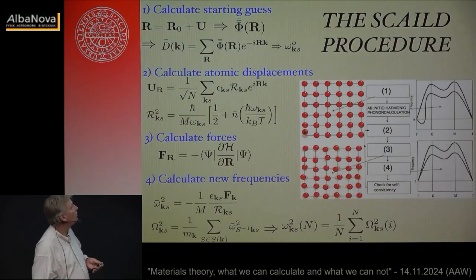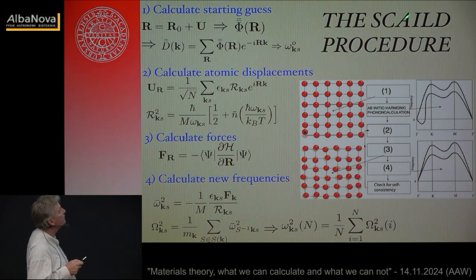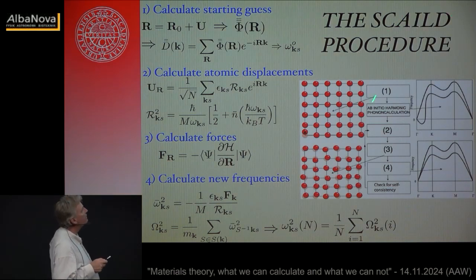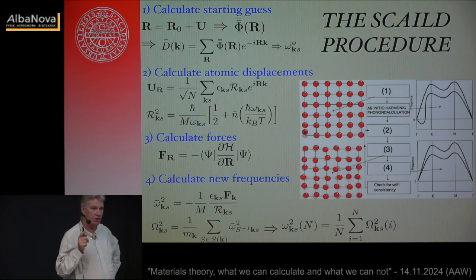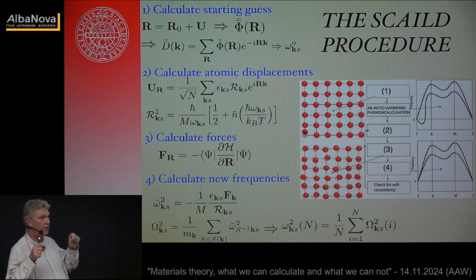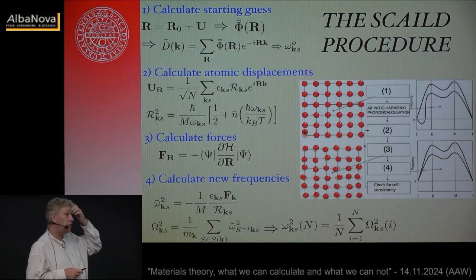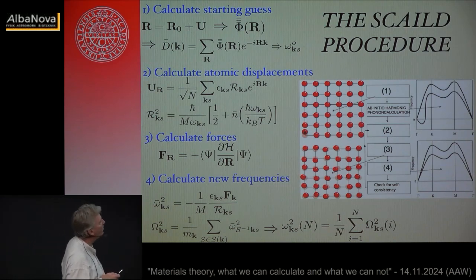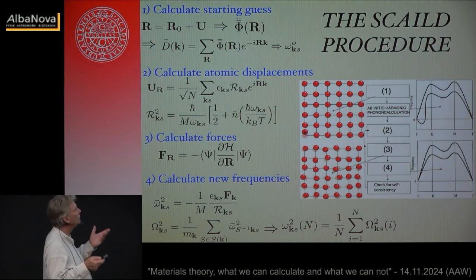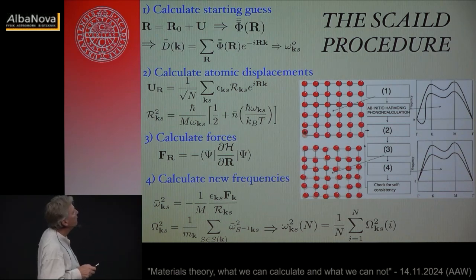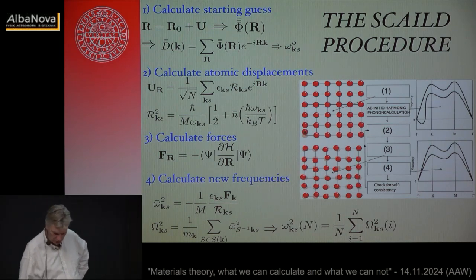So we came up with something we called the SCAILD procedure. SCAILD stands for self-consistent ab initio lattice dynamics. The basic idea is to say, no, it's not correct to just look at this force constant matrix for an ideally situated, perfectly crystalline structure. Titanium is BCC at higher temperatures, and therefore the lattice is not a stationary lattice. Things are vibrating and moving around a little bit, and that vibration, that movement, that entropy, our working hypothesis is, stabilizes this BCC crystal structure, and that is what one has to take into account if one wants to be able to reproduce the measured phonon frequencies. So we try to estimate how, at any temperature, these atoms are moving around. This mathematics here describes that, and I think I'll skip that and just show you instead what the results are.